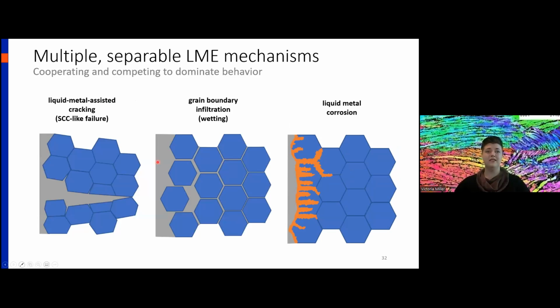So to summarize, we've got multiple separable liquid metal embrittlement mechanisms, and we may get both cooperation and competition between these mechanisms to see which mechanism or mechanisms dominate the overall behavior. When we look at liquid metal embrittlement through this lens of multiple mechanisms, some of these apparent contradictions in the literature start to actually make sense.